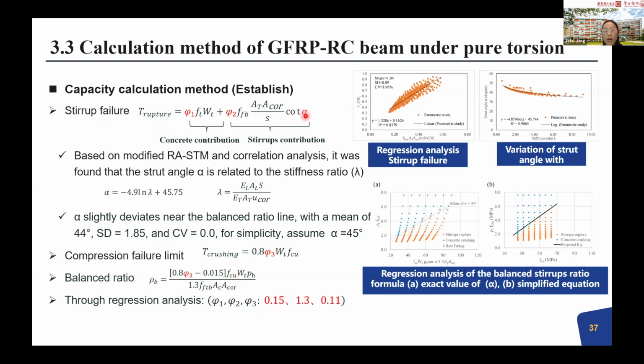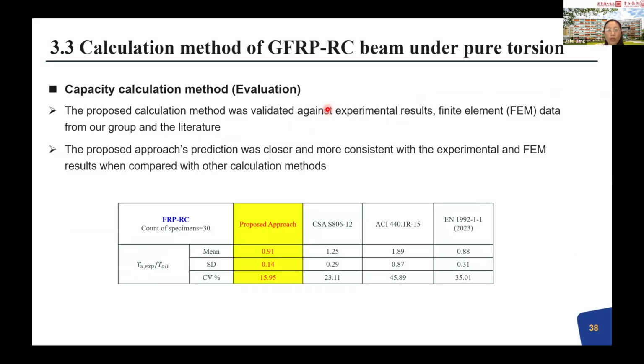Here, alpha, as I mentioned, is 45 degrees in our test observation. So we can simplify alpha equal to 45 degrees when using the design method. Later, in the standards chapter, I will further introduce the design method. Here is just the calculation method. Okay, so this is the evaluation. Our proposed approach gives predictions closer to the test results and even the numerical results.